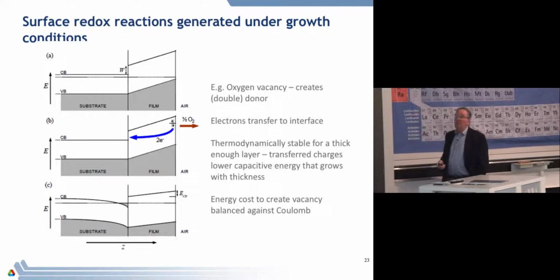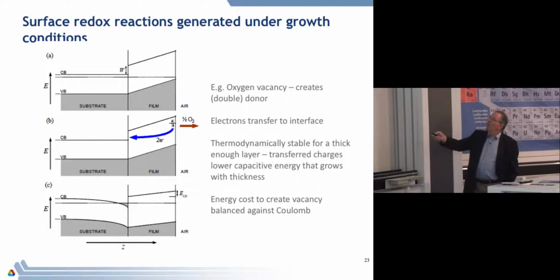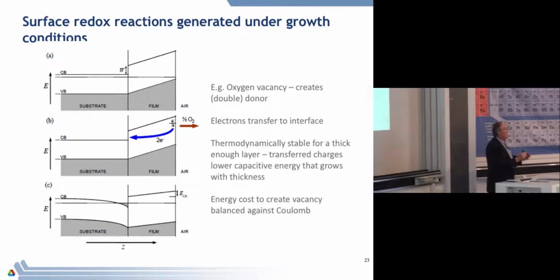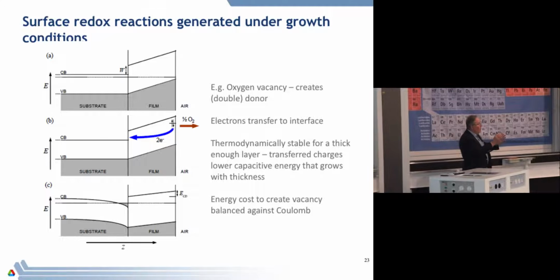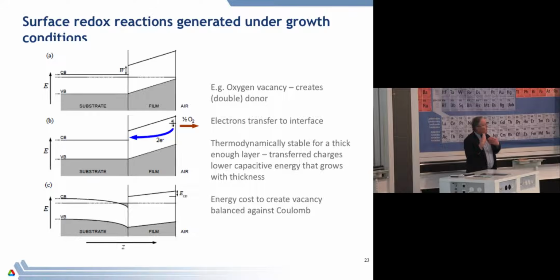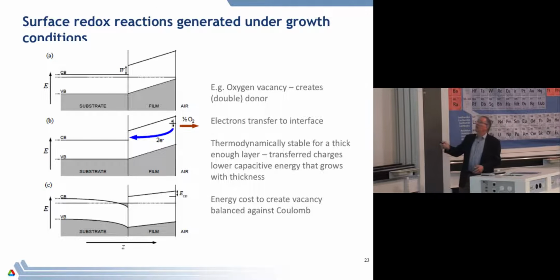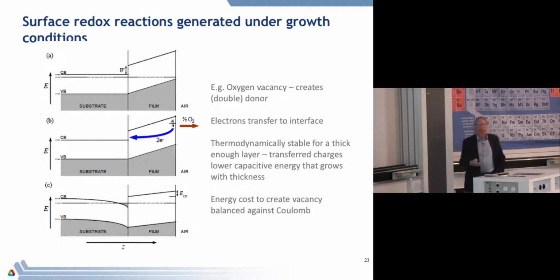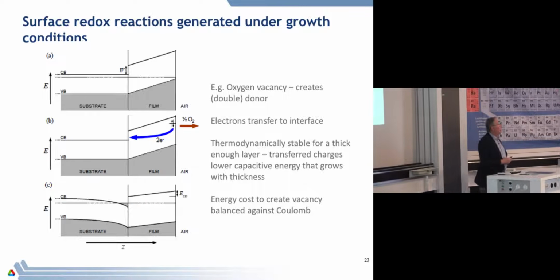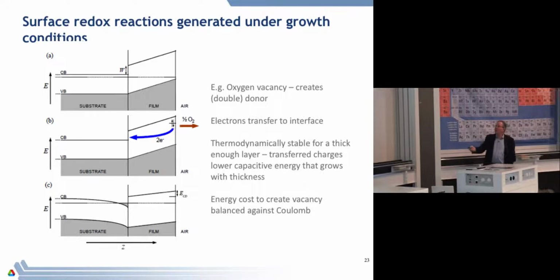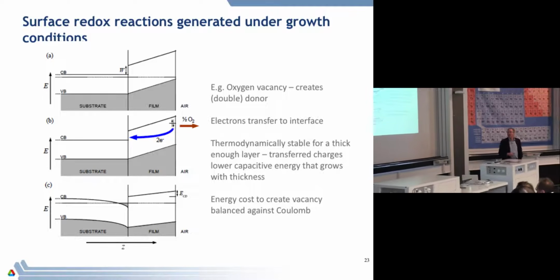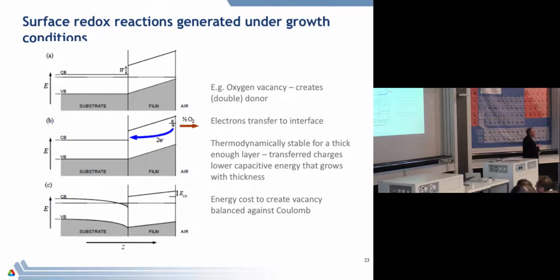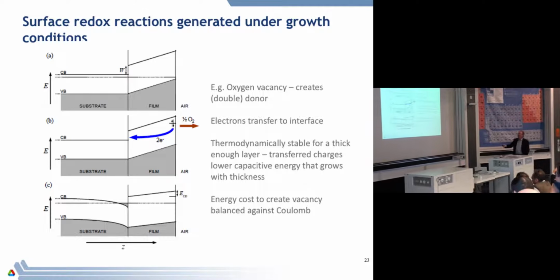What is thermodynamic? So as you grow thicker and thicker, of course, you will understand that these charge layers are getting further and further apart, and therefore the Coulomb potential costs you more and more energy as this grows. As you're doing this, you pay the energy of a vacancy, but you cut down the Coulomb energy because you screen the interface. Okay? So there's a very straightforward calculation that you can do to balance the Coulomb energy versus the energy of creation of a vacancy.